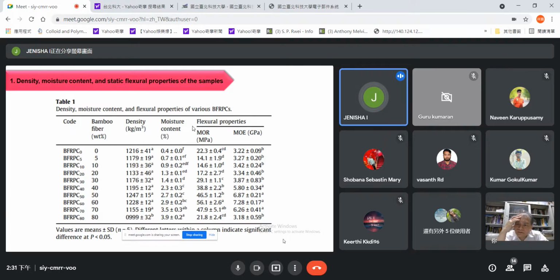This is because of the compression in the molding process, in the preparation process. The thickness would have increased because of some swelling in the mold. And then the second one is the moisture content. So there is a uniform trend followed in all these composites. That is, the moisture content increases with increase in the weight percentage, from 0 to 80.